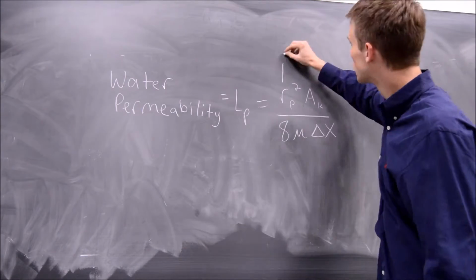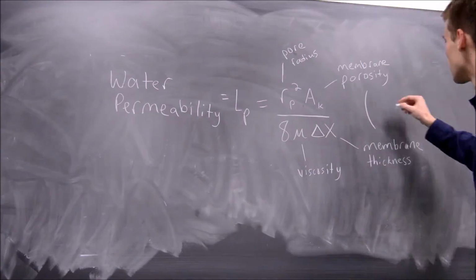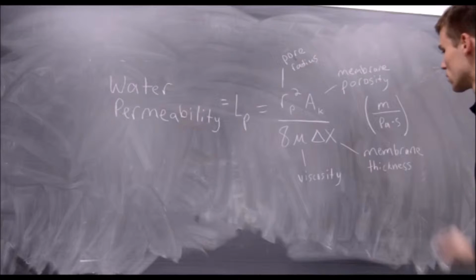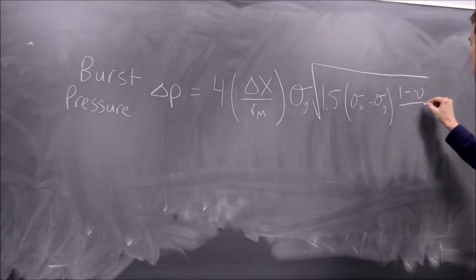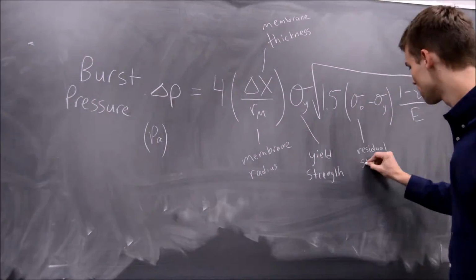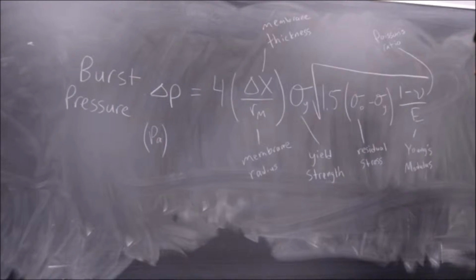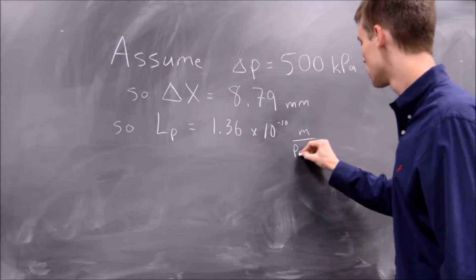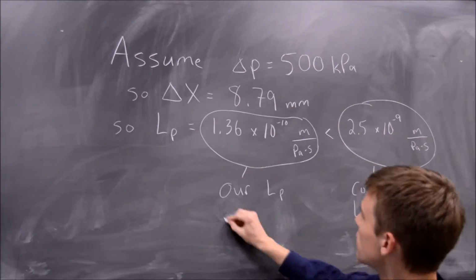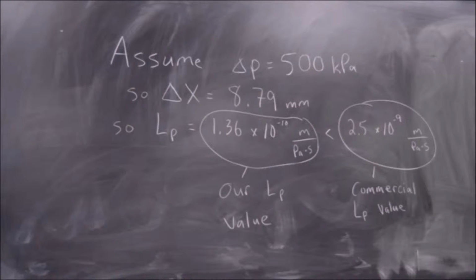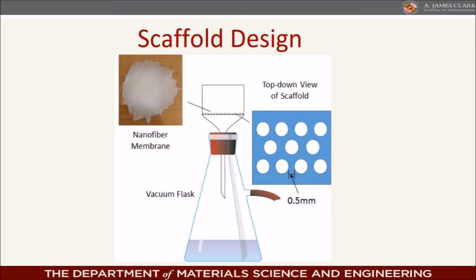We then began to design our nanofibrous PLA filters in order to maximize performance. From literature, we found mathematical models to determine both the water permeability and maximum operating pressure of our filters. Unfortunately, our model suggested that if our non-woven mats were to have sufficient strength for the pressure range of microfiltration, it would not offer a reasonable water permeability. However, we realized that we could increase the strength of our filters by directly depositing the nanofibers on a mechanical supporting scaffold. The next step became the design of the support, a porous scaffold.